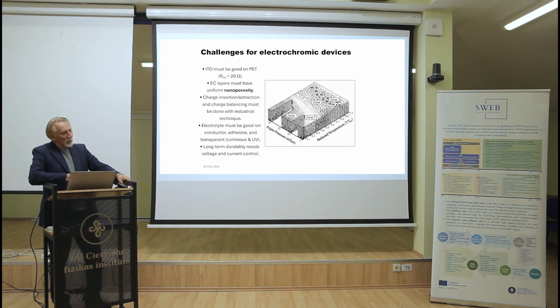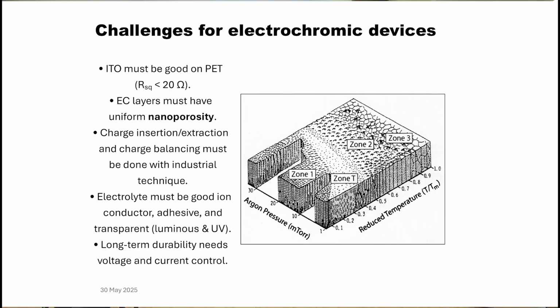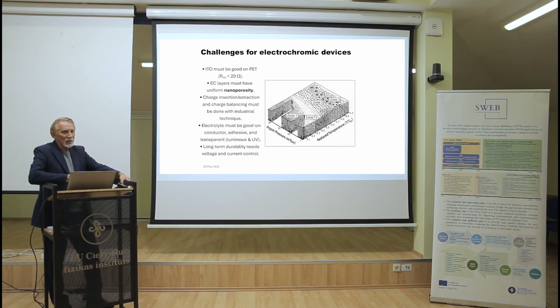The main also important question, as we use magnetron sputtering for deposition, is that the technology of deposition of this layer, starting from the transparent conducting thin film, depends on the power, on the gas, and on the temperature of deposition. So there are many things to adjust when we have a sputtering machine for depositing thin films.